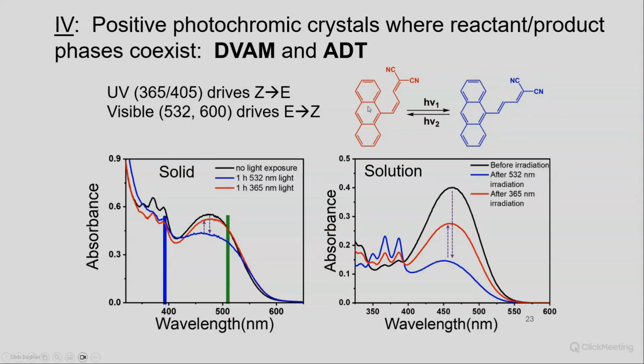But this just shows that this in solution, this is just your standard, very similar actually in many ways to azobenzene, undergoes an EZ photoisomerization in solution. It's at least partially reversible by irradiation, so you can irradiate in the visible, and then you can reverse it or partially reverse it by irradiation in the blue. In our case, it should be 405. For some reason, that light is shifted slightly. And so in solution, that's all you do. And if you shine both 405 and 365 or 405 and 532 nanometer light, you get a photostationary state, the sort of standard photochemistry in solution.